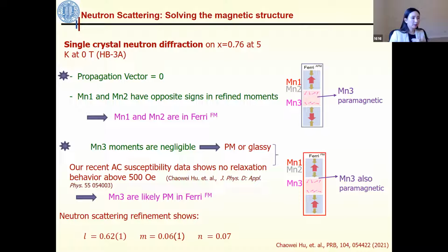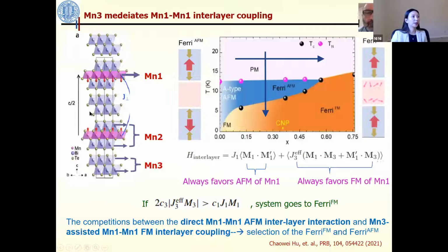And then from the neutron scattering, one very interesting thing is the observation for the manganese 3 moment is actually very small. It's almost 0 within the experimental error bar. So that just suggests that the manganese 3 here is either paramagnetic or just glassy. And our recent AC susceptibility measurement shows there was no relaxation behavior above 500 oersted. So therefore, the manganese 3 are likely paramagnetic at low temperatures. Okay, so that was the understanding of magnetism here, right? We have manganese 1, manganese 2, and then we have a paramagnetic manganese 3 here.